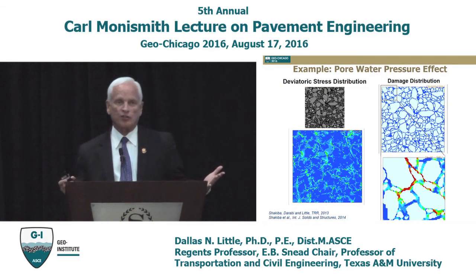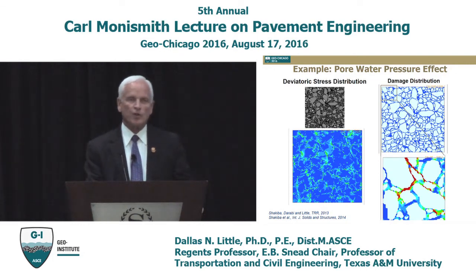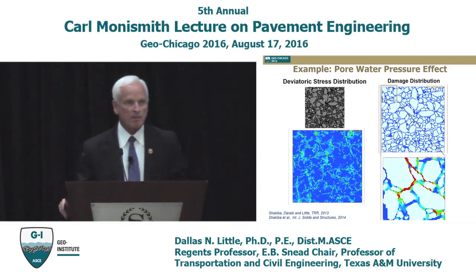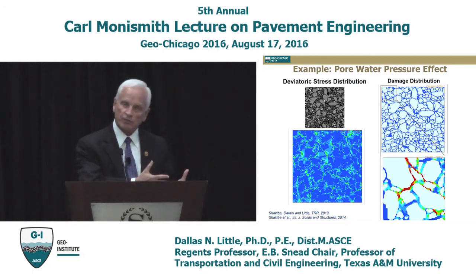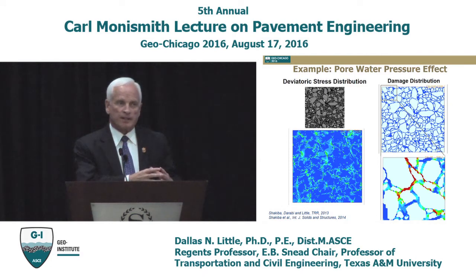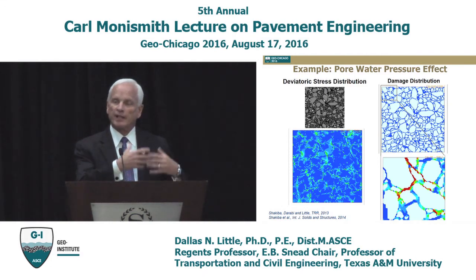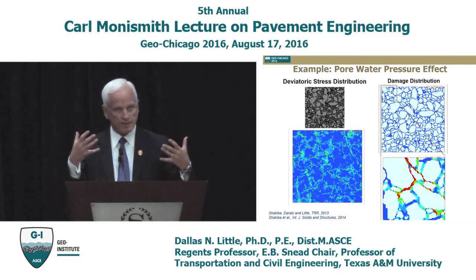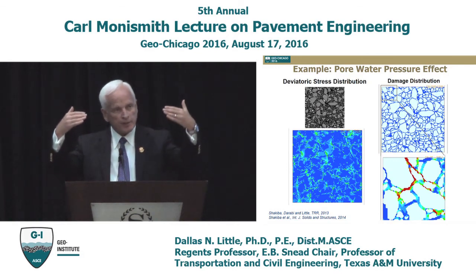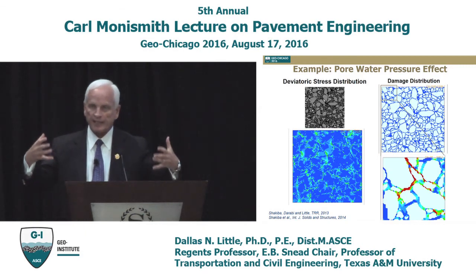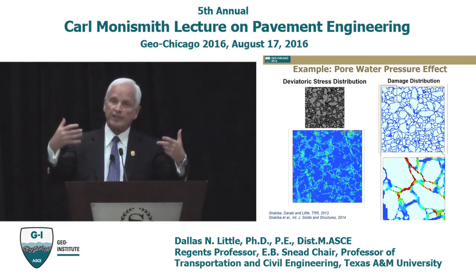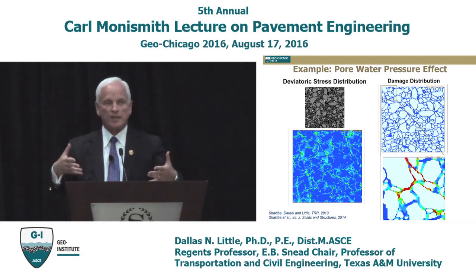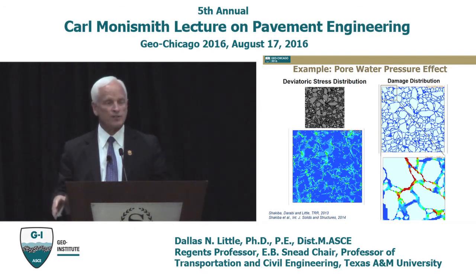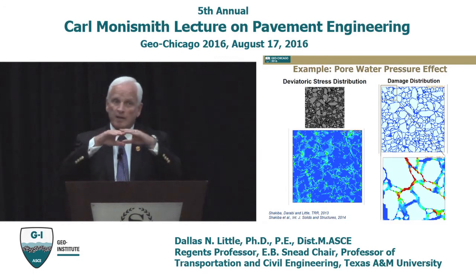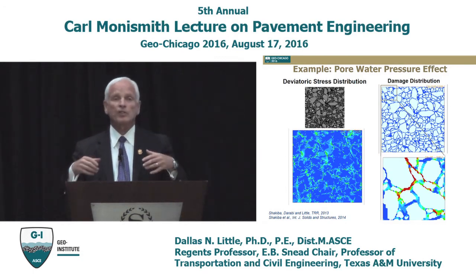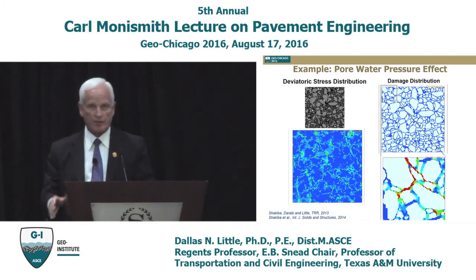All right, why did I show this? Well, I thought this was a good way to show you how Panda has the capability of taking mechanical damage and coupling the mechanical damage with the effect of moisture. So as moisture penetrates and diffuses into the system according to a recognized law like Fick's law, where we define the diffusivity, and we couple in the mechanical load with it, then we can visualize the damage process. We can do this at the mixture scale, the micro scale, or we can do it at the global scale or the pavement scale.